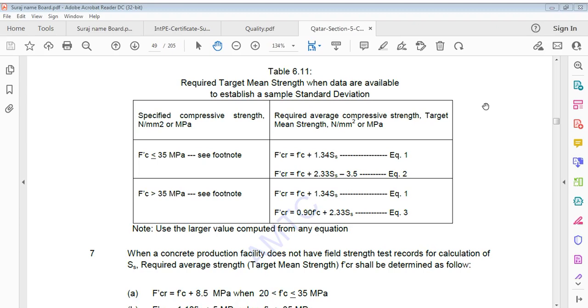In this case F-CR is the required average compressive strength, the target mean value of strength. This is F-C plus 1.34 S-S, the standard deviation. That's equation 1. The other one is F-C plus 2.33 S-S minus 3.5. That is equation 2. When F-C is greater than 35 MPa, in that case F-CR is F-C plus 1.34 S-S as before, and the other is F-CR equal to 0.9 F-C plus 2.33 S. Now we apply a 10% reduction factor here, that is 0.9 F-C plus 2.33 S, and that's the number.